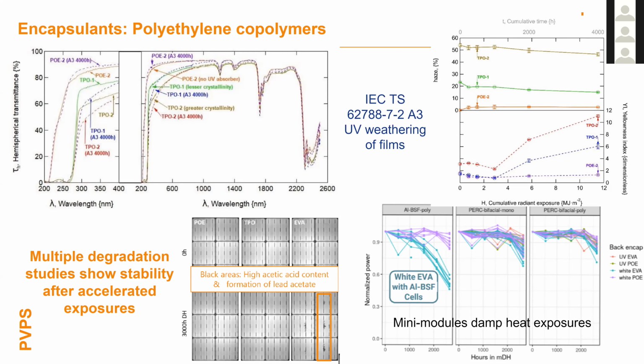Another thing here, this bottom figure is mini modules exposed to damp heat and thermal cycling. They were in damp heat, then switched to thermal cycling afterwards, and then back into damp heat. The x-axis here is the number of hours they were in damp heat. These are 3 different cell types encapsulated together, with UV cutoff EVA and UV cutoff POE, white EVA and white POE. What you see in this bluish kind of color is white EVA encapsulant -- huge power losses in those mini modules, and only in Al-BSF cells. We don't see these in the PERC, 2 different types of PERC cells.